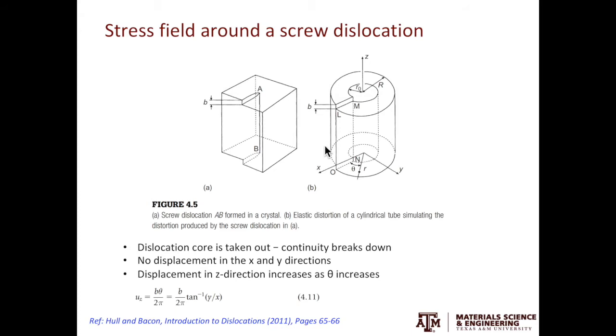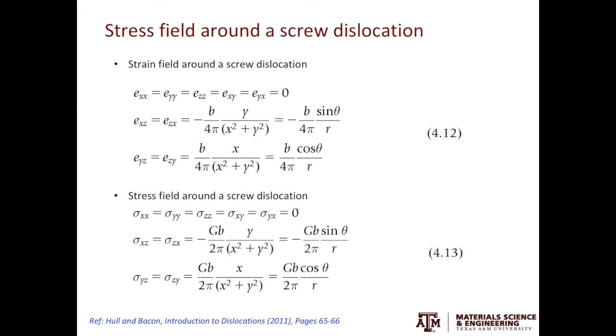If you look at the displacement caused by the screw dislocation core, all the changes happen along the z direction, while there is no displacement in the x and y directions. If you go around from the origin by 360 degrees, the z value changes as theta increases. Since there is no displacement along the x and y directions, the strain along the xx, yy, xy, and yx directions are equal to zero. Along the z direction, there is no normal strain either, so the strain Ezz is also equal to zero. However, there is a shear along the z direction, so the strains along the xz, zx, yz, and zy directions are non-zero. They can be expressed as a function of theta and r in the polar system, or x and y in the Cartesian system.